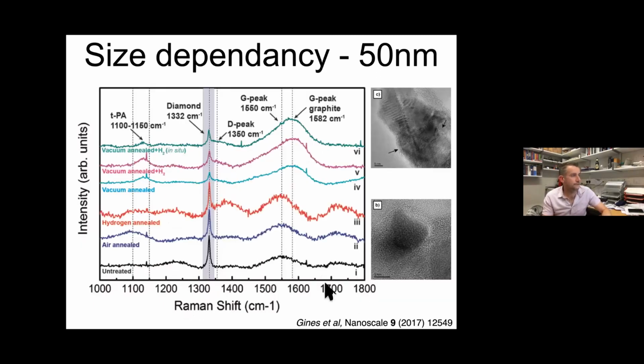If you then go to the Raman, I won't go through all of it because Raman is really boring, but basically, you see in the ones that we've annealed this G peak, right? This 1582, which is directly related to these rings, the things that we're seeing in the TEM. So this is just for the people that don't believe the TEM. Fair enough. Yeah, I know what you mean. So basically, if you create these, you can make it react.